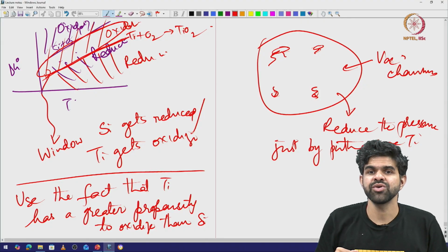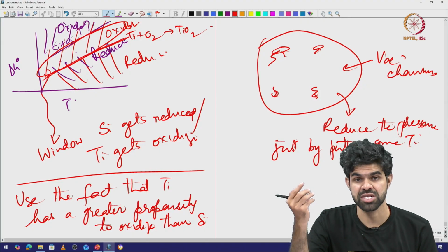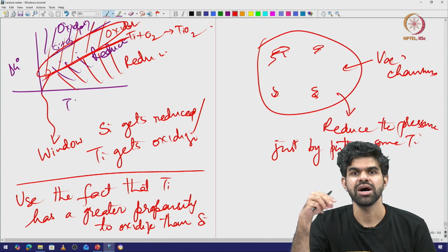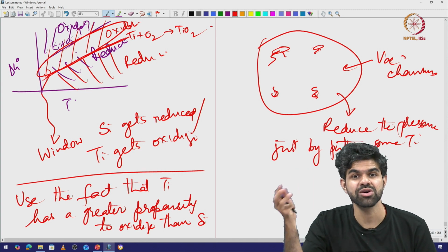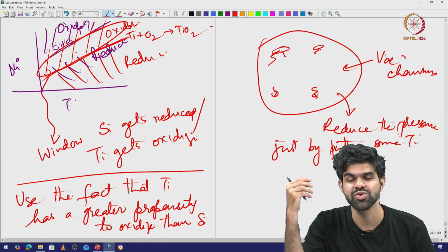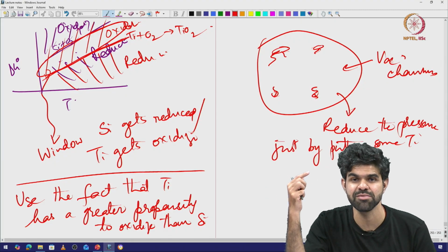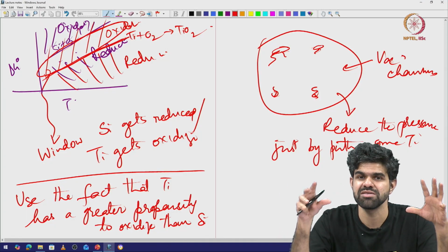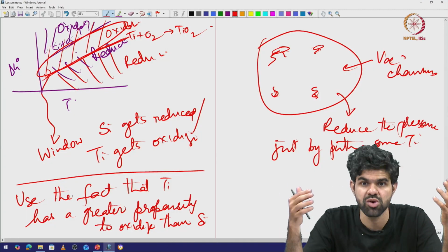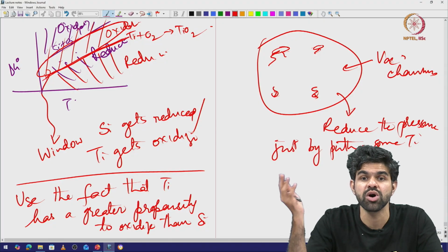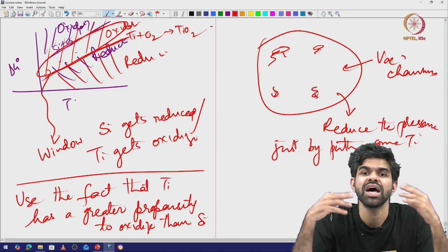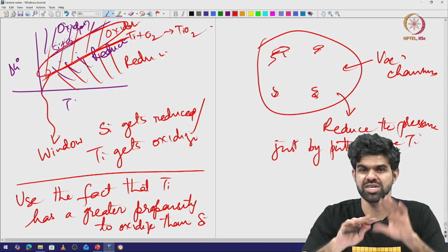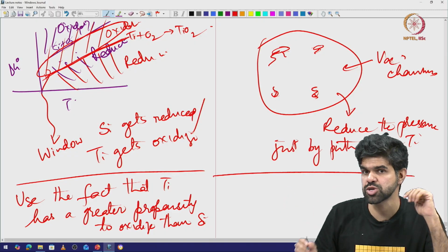And you have what are called titanium sublimators, which are also used to create ultra high vacuum. You sublimate titanium, and then that picks up oxygen, so you don't have oxygen in the chamber anymore, and you can reduce the pressure inside the chamber. So this is a well-known technology: titanium gets oxidized at the cost of the oxygen that is already available, and so I can reduce pressures inside vacuum chambers. Okay, so that's known.